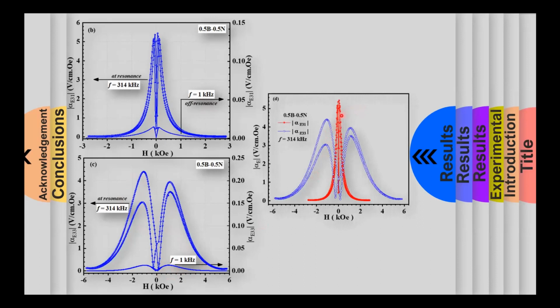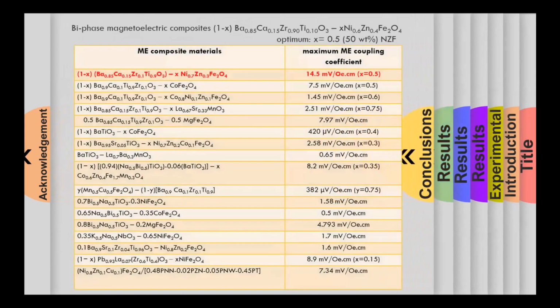And when we compare this magnetoelectric voltage coefficient obtained at the resonance between the transverse and longitudinal, we see that the transverse mode has a higher response than the longitudinal, though the difference is small, which is very similar to the observations that were made in the off resonance condition. So I would conclude by saying that biphase magnetoelectric composites with BCZT and nickel zinc ferrite were successfully formed, and they showed their individual ferroic properties. That is, they showed the bulk ferroelectric property as well as the magnetic behavior, and they also showed the coupling between them. And the maximum magnetoelectric response was observed for the composite which had 50 weight percentage of nickel zinc ferrite. And when we compare the values with some other composites containing not only lead-free piezoelectric phase, but also some lead-based piezoelectric phase, our values are pretty much higher.